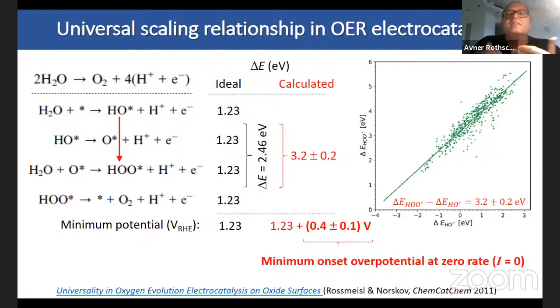In reality, different steps have different energy barriers, and specifically, it was found by looking at many different electrocatalyst compositions that the barrier between the first intermediate and the third intermediate, instead of being 2.46 electron volt, is 3.2 electron volt. So it means that we have a minimum overpotential of 400 millivolts, and that is before the reaction occurs. That is at 0 rate. So that is called the minimum onset overpotential, which for the oxygen evolution reaction, because it's a 4 electron reaction, basically you have a huge loss of efficiency here.